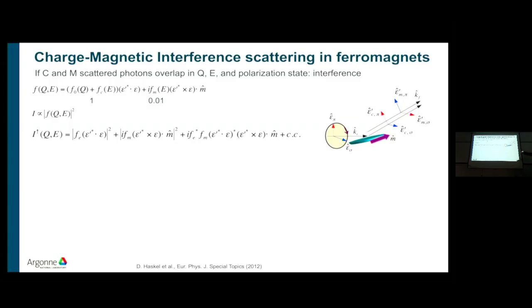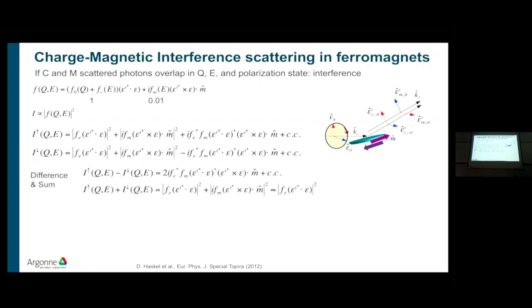So if I get that quantity, remember we call this 1, this is about 1%. I square this quantity, this is the direction of the magnetization, I get this term squared, I bundle F0 and Fc, non-resonant and resonant charge, into this Fe, I get this term squared, and then I have the cross product plus the complex conjugate. And if I change the direction of the magnetization, this term, which is proportional to the direction of the magnetization, will change sign, but these two terms don't, because this is independent of magnetization. This one goes like the square of the magnetization. Now I take the difference between these two, and I end up with this term. These two cancel, and I end up with this charge magnetic interference. And this charge magnetic interference has information on the direction of the moment and on the magnitude of the moment through this magnetic scattering factor.